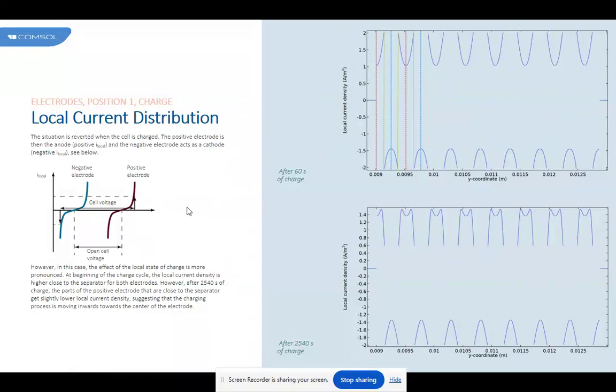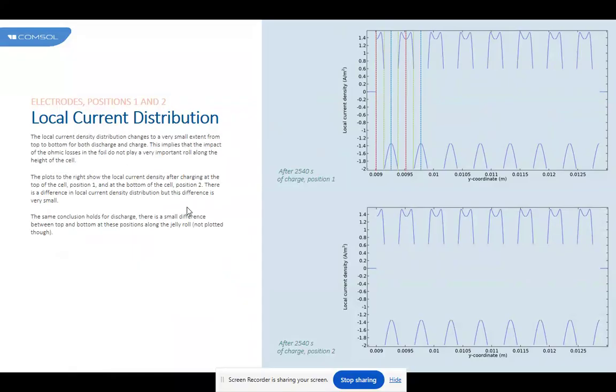However, after 2540 seconds of charge, the part of the positive electrode that is close to the separator gets a slightly lower local current density, suggesting that the charging process is moving inwards towards the center of the electrode.